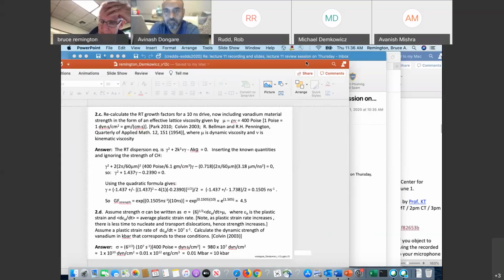I think it's one I hope that people will address going forward: if you generate dislocations in one phase and now you transform to another, are they still there? Do they get absorbed into boundaries as the phase is changing? And then the question is, do you end up with a much finer grain microstructure? Is the microstructure more highly textured because of that? So there are lots of really interesting questions, and I hope some of the students tuned in will take that up in their career and really understand what's going on in these systems.